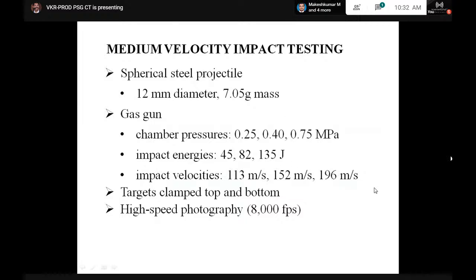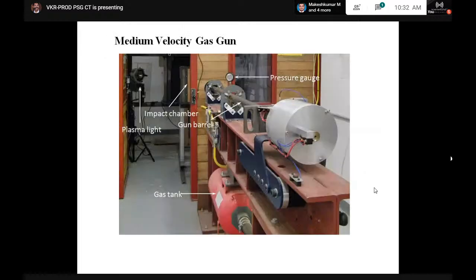The target was clamped in a fixture, and high-speed photography was used. It can take 8,000 frames per second. This is the capacity of the camera that was used to capture the behavior of the composite when the spherical steel projectile hit at a particular velocity. So this is the medium velocity gas gun.